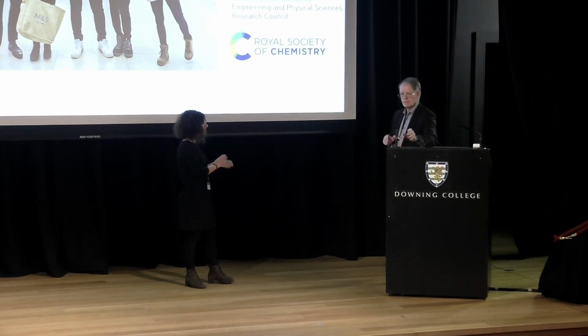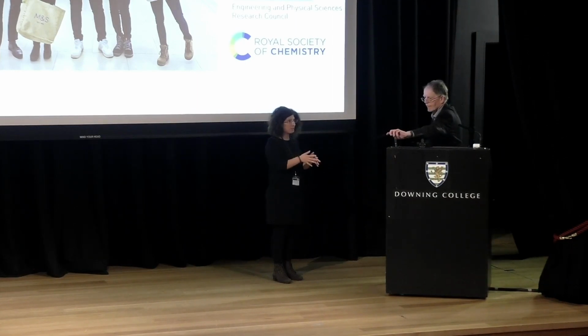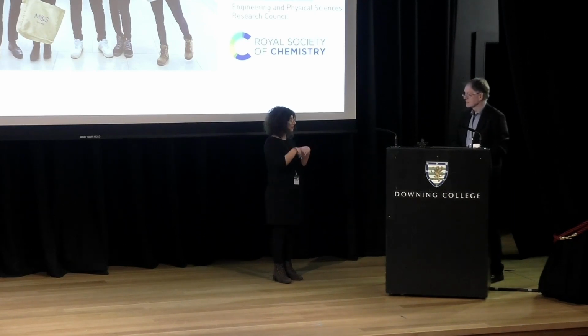So it is and it isn't, in the sense that they can work against each other, as in sometimes you mix one polymer with another and you try to make nanoparticles with it and it just doesn't work, as in the plates would not grow, or you won't get a good control over morphology. But most of the time, actually, you're able to make it work, because we can have different layers in it. If 2 polymers are not compatible with each other, you can have a mid layer of a polymer that is compatible with the one that you have and with the one that you want to add, and so you can grow that this way. So the fact that we can grow multiple layers in it plays to our advantage in terms of going against polymer non-compatibilities sometimes.